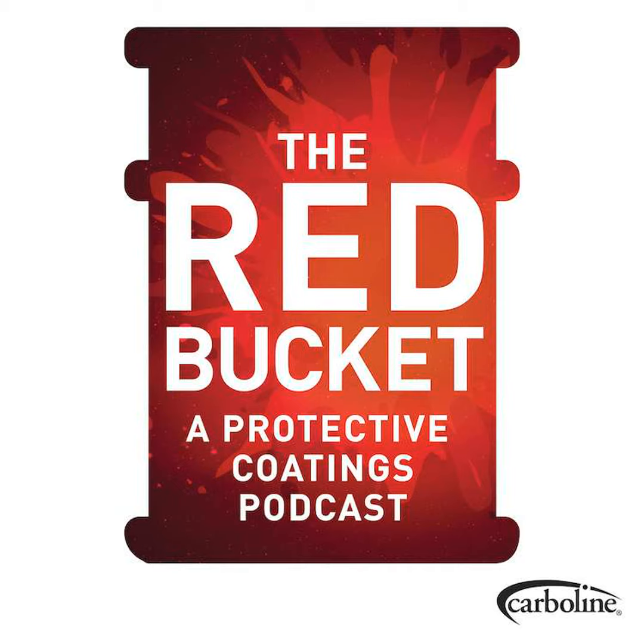However, the thing that every inspector should have if they're doing concrete jobs is, especially if it's specified this way, and specifiers should definitely be using this method to guarantee that you get the profile needed. Because as we know for steel, and we've talked about profile and coating thickness and everything else, it is so important. We're increasing the surface area so that we can get better adhesion, and we're going to need more surface area depending on, like you said, the harshness of the environment. And so these standards are 3D. There's no question whether or not the surface profile that was desired was achieved with these standards.